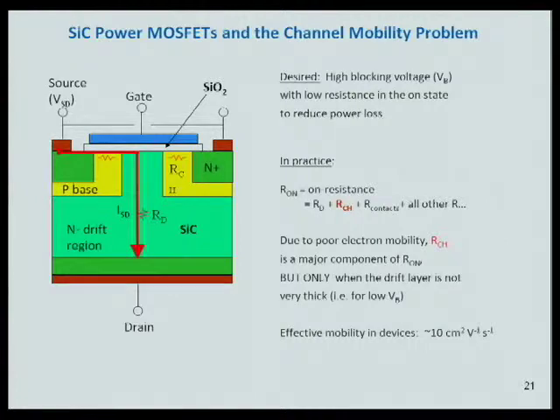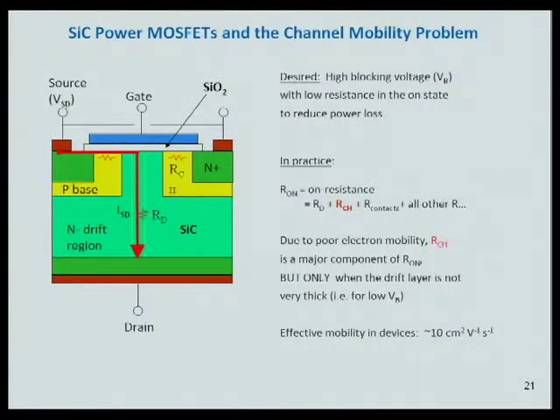Here we have our gate, our SiO2 oxide. The electron current is going from the source, which forms a ring around this. It's traveling under the gate, and then it's traveling down through the bulk of the silicon carbide. So we have the channel, which is the current flow under the gate, and that's where the mobility is extremely low. In our device, the total on resistance is primarily the sum of the drift region resistance and the channel resistance. For devices that have a very small drift region, the channel mobility dominates the on resistance, and that limits the effectiveness of these devices.